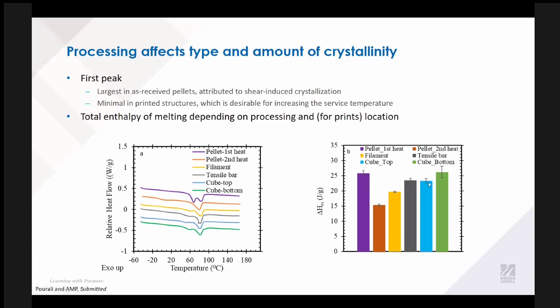And then one of the things I think is really interesting about this is if we're printing a single sort of cube, looking at the top versus the bottom, we see that there's a lot higher crystallinity in the bottom than the top of this. And so this is another challenge, but maybe also an opportunity if you're trying to think about having gradient properties. This is something that arises naturally from this type of system.